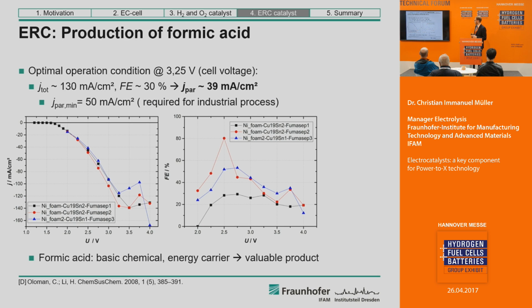And I will show you the result on my last slide, I think. You see here plotted in the left figure the current density versus the cell potential. If we increase the cell potential, we see that after a certain point the current density increases, which tells us that the reaction takes place. And you see that the reaction increases by increasing the cell voltage, and after around, I think, 3.3 volts, we have a limiting character, so there's no further increase of the current density by increasing the cell voltage.